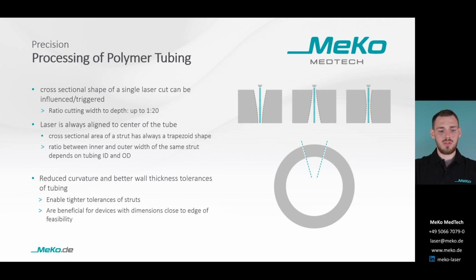A lack of material uniformity, like shifting wall thickness or shifting outer diameter, has a bad impact on the cutting accuracy, and the parameters cannot be set with a sufficient precision. An important limiting factor is the ratio between the cutting width and depth, which can be up to 1 to 20. This means for a material thickness of 200 micrometers, the smallest possible cutting width is around 10 microns.